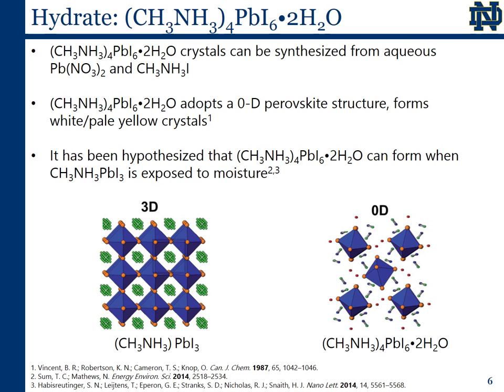Looking at previous literature on the interaction of water and methyl ammonium lead iodide, we find that Vincent and co-workers previously reported on the structure of a hydrate of methyl ammonium lead iodide, which can form upon the addition of lead nitrate to an excess of aqueous methyl ammonium iodide. This hydrate species forms a pale yellow-white crystal and adopts a zero-dimensional perovskite structure containing isolated lead iodide octahedra. In addition, several groups have suggested that this hydrate could form when methyl ammonium lead iodide films are exposed to moisture in the air. Because of the similarities between this reported hydrate and our degraded perovskite films, we chose to investigate this connection further.